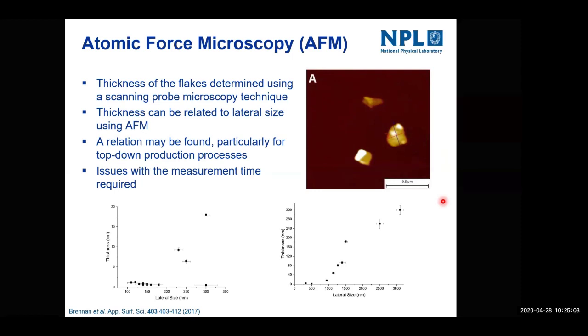At the same time, for both AFM and SEM, you could see why the sample prep becomes so important, because if you do not prepare the sample in the correct way, you can't get a good measurement of the thickness because the flakes aren't isolated, but you can also skew the results of what you think the material is, depending on how you prepare it. So some preparation methods don't work because they remove parts of the size distribution. If you think of that graph, it might be that bigger or smaller particles are removed.